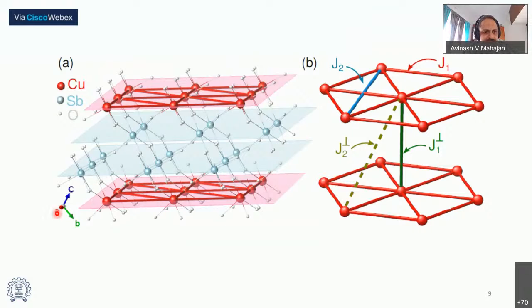So we are looking at these ABC lattice parameters, and these marked red lines suggest interactions between the nearest neighbor coppers. They are also shown in the figure on the right, where you have J1, which is the nearest neighbor copper-copper coupling, and J2, which is the next nearest neighbor within the plane. And then there's a possibility of interplanar coupling through these J2 perpendicular, etc. Okay, so these are the parameters which ab initio will evaluate based on finding the overlap integrals and so forth.